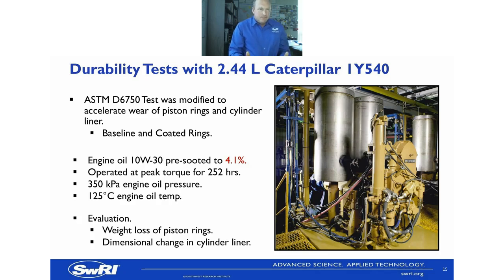Now that's okay if you get low friction, but we're also needing to know that this is going to last. So we also took this and we did some durability tests with a 2.4 litre Caterpillar engine. This is a standard ASTM engine test. We modified it to accelerate wear of the piston rings and cylinder liner. So baseline and coated rings were run in it. We do weight loss of the piston rings and dimensional change in the cylinder liner. I haven't gone into details here.